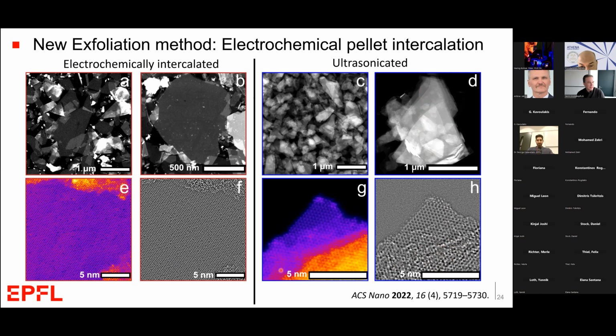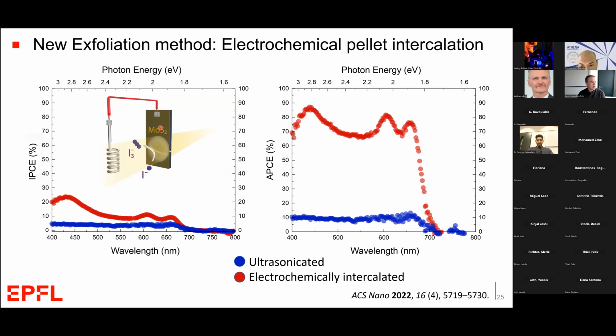The best results we have on this are on a slightly different system where we used molybdenum sulfide and a sacrificial photoelectrochemical reaction. Comparing the ultrasonicated flakes to the electrochemically intercalated flakes, we see a huge difference in their absorbed photon to current efficiency. Now we're achieving almost 90% of the photon conversion efficiency based on the absorbed photons in these electrochemically exfoliated flakes. Moving this towards tungsten diselenide and demonstrating hydrogen evolution with this technique is currently underway in our lab.